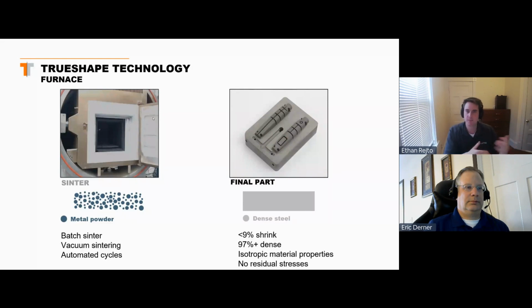Because in the printing step, we are drying and removing those solvents, we have a very, very dense green body density. That means there's not a lot of porosity in the green body, so the part does not have to shrink as much as in other processes because it's already very dense. And of course, the lower your shrink rate, the better, because that's what allows us to control our dimensional stability so well and allows the part to come out of the furnace with that 1 thou per inch tolerance that I mentioned before.